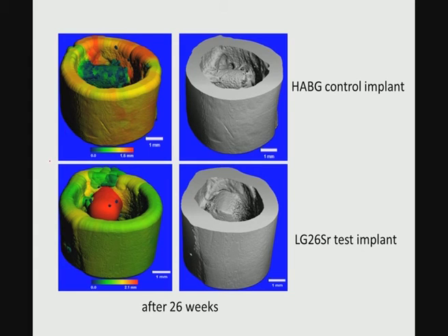The same is however not true for the control implant, and this is after 26 weeks. You see mostly green color contrast around the implant, essentially meaning that the tissue thickness or bone tissue thickness on this control implant is certainly not towards the red region, but less than that. So, from the tissue thickness also, you can quantitatively understand the tissue or bone regeneration around the implant.